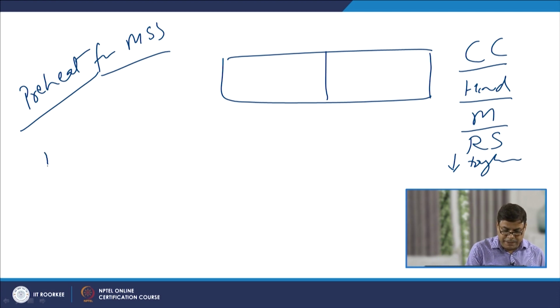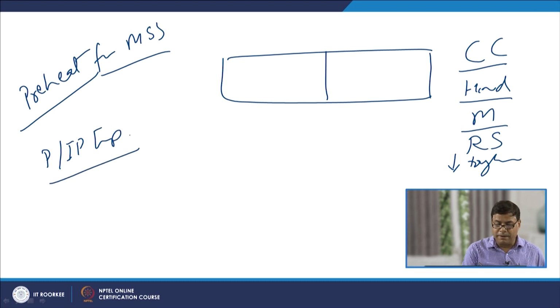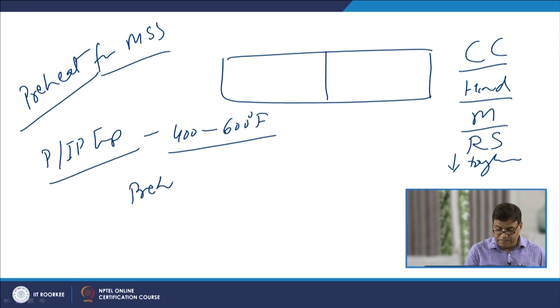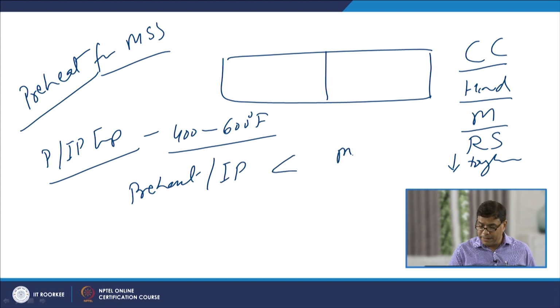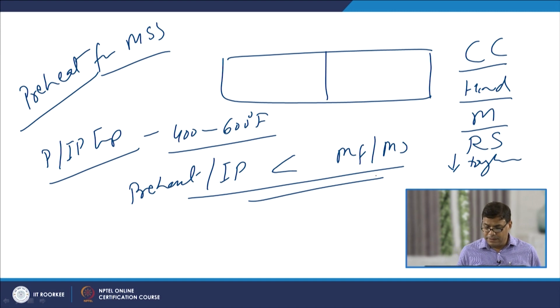So, normally the preheat as well as the interpass temperature which is used for welding of the martensitic stainless steel ranges from 400 to 600 Fahrenheit. We do not use a preheat or interpass temperature that is less than the MF or MS temperatures. This is another point which should be kept in mind while deciding the different preheat values of the temperature.